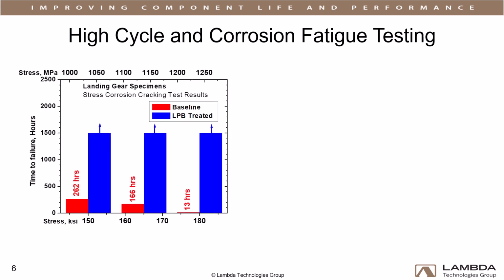Untreated material failed in only 261.8 hours at 150 ksi, 166.5 hours at 160 ksi, and only 12.9 hours at 180 ksi. The LPB process specimens did not fail even after 1,500 hours of exposure at all 3 stress levels. When the specimens were loaded to higher stress levels in an attempt to force failure, the specimens were severely bent without ever cracking.